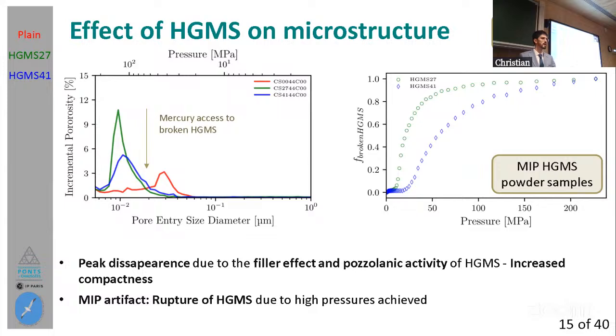So we saw that peak there, and we thought that maybe it was related to some difference in the microstructure of the cement paste that happened due to the presence of the spheres. We were just trying to understand these results because it was quite difficult. And when we arrived at this idea of breaking the spheres, which was perfectly aligned with all the results that we were obtaining, it was already too late to keep doing tests, but I completely agree that it would have been great to have done this kind of test to verify the supposed improvement in the compactness of the matrix due to the use of spheres.